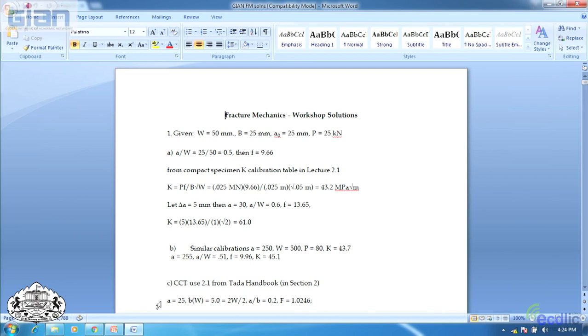Now, I don't have all the details, but part B is W is 500 and A is 250. So it's just a 10 times planar size specimen and same thickness. And then I got K of 43.7, about the same. Now when I increased crack size 5 millimeters, so 255 millimeters, A over W just goes up to 0.51 and F just goes up a very small amount. So K went up to 45.1.